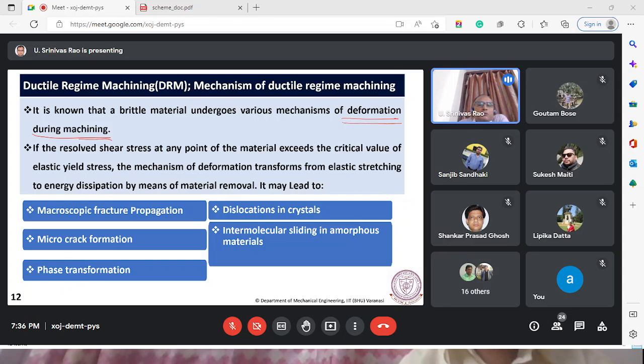Okay. And if the resolved shear stress at any point of the material exceeds the critical value of elastic yield stress, the mechanism of deformation transforms from elastic stretching to energy dissipation by means of material removal. Through this, what we can achieve is macroscopic fracture propagation, microcrack formation, phase transformation, dislocations in crystals, intermolecular sliding in amorphous materials. These things give a window of opportunity to have some deformation in machining, and we can explore that for machining.